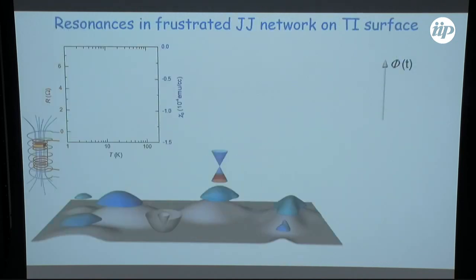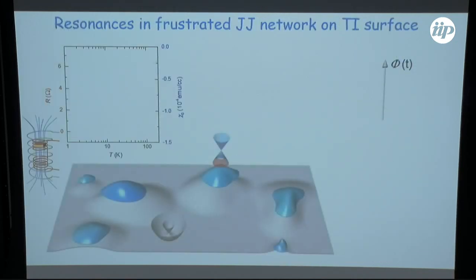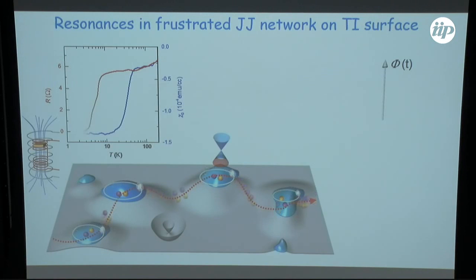So our picture was here. And you see, this is sort of a cartoon of what we have. We have Dirac puddles, and we have this strong spin-orbit coupled 2DEG, a high mobility 2DEG. And first, you start screening in the puddles, and that's what we see in susceptibility. And eventually, the same long-lived quasi-particles that contribute to quantum oscillation also mediate Josephson coupling and eventually a proximity percolation path that gives us the global TC. So the question we ask is, of course, this is not the only path, and this is a messy system.